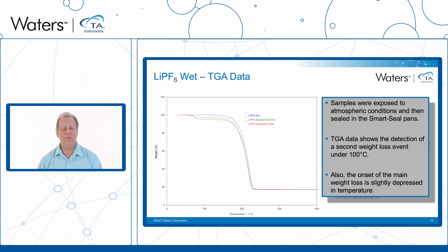And we can see here that even as fast as 5 seconds, you can tell through the TGA data alone that this material has been contaminated by water vapor. There is a second transition that's occurring now below 100 degrees Celsius, which again is not apparent in the dry material. And we also see here that the weight loss onsets for the main decomposition are somewhat slightly depressed. Remember, for the dry material, everything was laying on top of one another. The reproducibility did not show any of that.